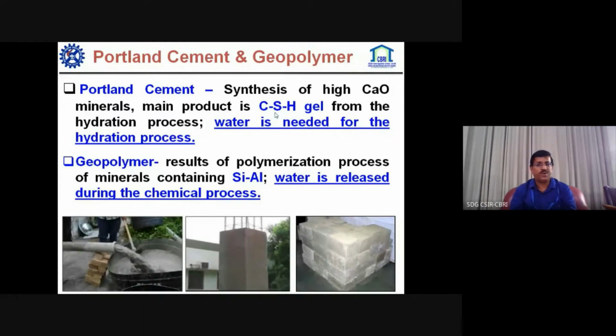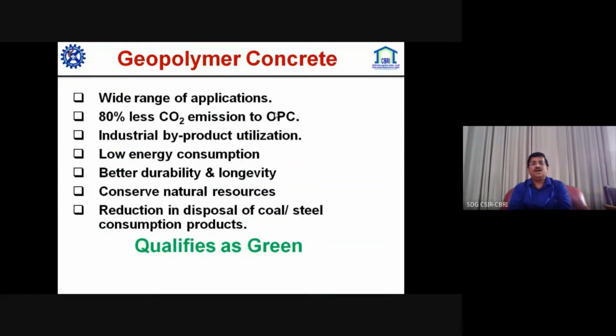Whereas in geopolymer, it has nothing to do with hydration. It is a polymerization process, but polymerization of inorganic material, minerals which have sufficient silica and alumina content, and in this case water is released, or comes out, during the chemical process. So we don't need any water; rather, if you heat it, strength will be better and more polymerization reactions will take place. It is qualified as a green material, and it reduces CO2 emission by about 80% compared to ordinary Portland cement.